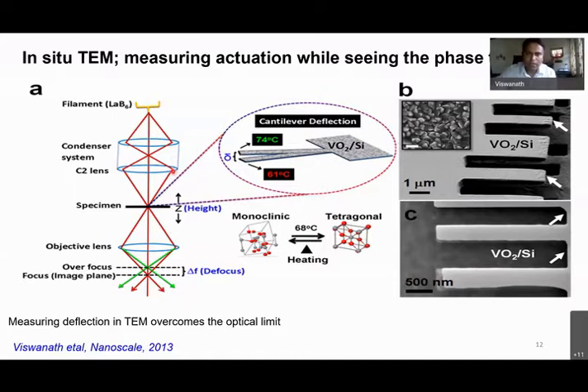So when the sample is going up or down, of course, I will not have the proper focused image. So the focus would be changed, but the focus can be corrected back with the use of the defocus knobs. So every time, I'm going to increase the temperature, maybe in steps. Whenever the cantilever goes up, accordingly, I would be able to correct back and bring the cantilever tip into focus, note down the defocus value.